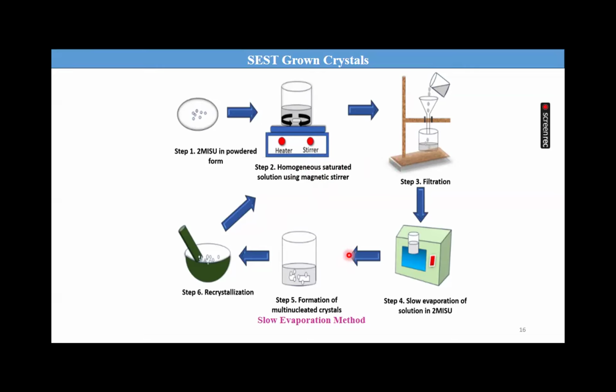Moreover, the beaker was tightly covered with polythene sheet wherein tiny holes were made so as to ensure crystallization by solvent evaporation. The growth system was kept in a dust-free ambience maintained at a controlled room temperature in order to ensure slow evaporation of the solvent. After a few days, white-colored 2MISU crystals were successfully grown, and the grown crystals were allowed to undergo a recrystallization process in order to remove the impurities present, such that this process would improve the optical quality of the single crystals.